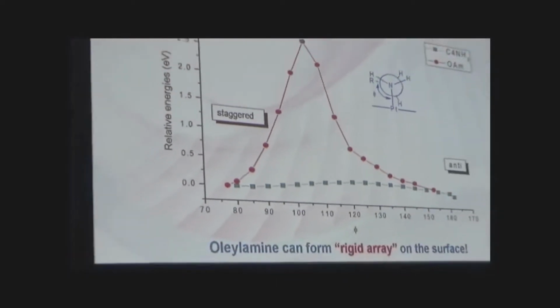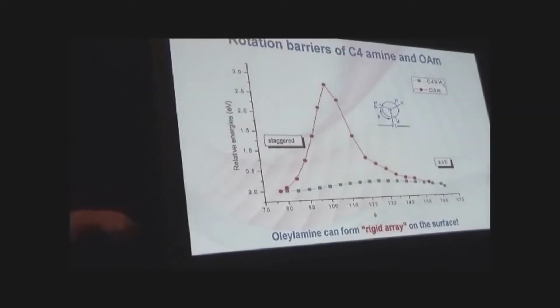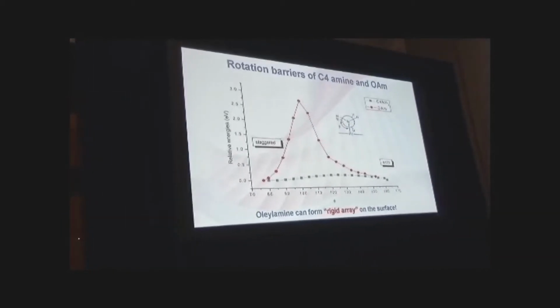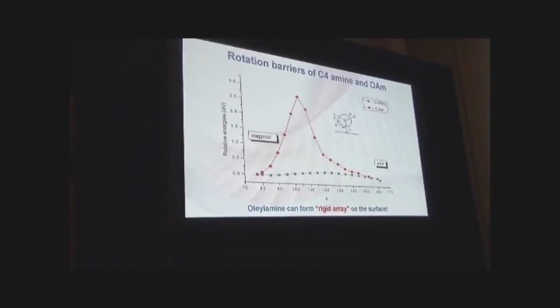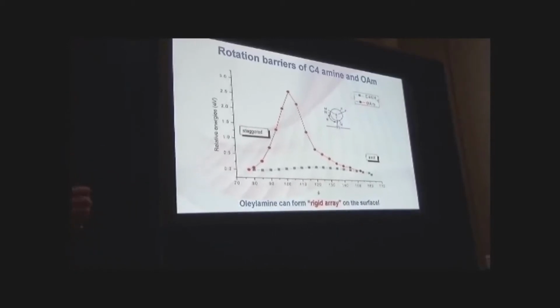We also calculated the rotation barrier. For the short carbon chain, the rotation is feasible. The barrier is only about 0.1 eV. And for the long-chain organic amine, the rotation requires about 2.8 eV, so it cannot rotate on the surface. So the organic amine can form a rigid array on the surface. It can create some unique sites with a steric effect.